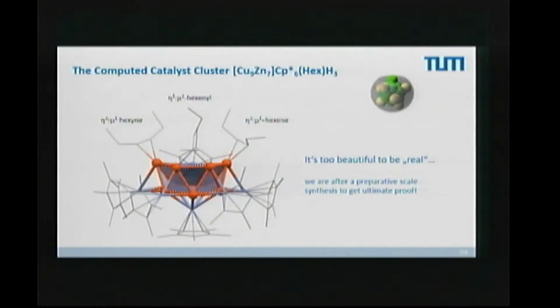Message is, we could show that this cluster is a pre-catalyst in the chemistry of the alkyne semi-hydrogenation, and there is a huge reorganization of this cluster under the conditions of the ongoing catalysis. So this is how this cluster looks like as it comes out of the computer. And since I am trained as a skeptical chemist, as an inorganic synthetic chemist, I don't believe what the computer is telling us. I just hope it might be true.